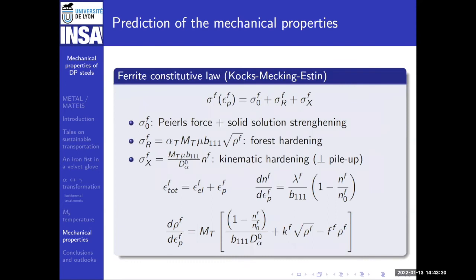So first, we take a constitutive law for ferrite. I'm going to go quite fast because it's something that you know. It's a classical Kocks-Mecking-Estrin law where you have the contribution of kinematic hardening, the contribution of the forest hardening, and the base stress, Peierls force plus solid solution hardening. So here are all the equations that you need for this classical Kocks-Mecking-Estrin approach, where you have this law that combines all the stresses. You calculate the forest stress due to the dislocation density here, and you have an equation of evolution of the dislocation density as a function of strain with annihilation and multiplication terms. This is nothing new.